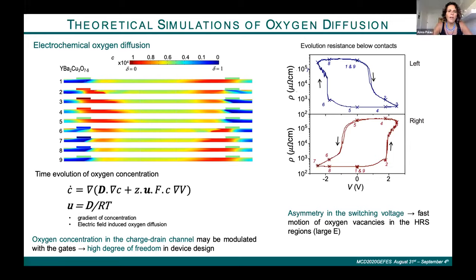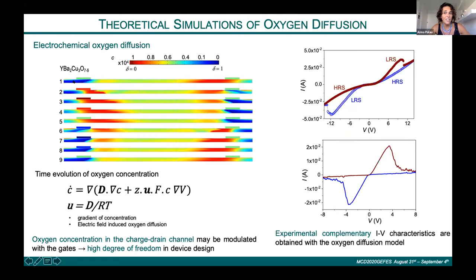Yeah, I think that we have all the effects in the same experiment, and we think it's quite interesting to use different experimental tools to not just evaluate the oxygen content, but also to evaluate the real charge current density and charge ordering, for example in a gradient induced by this kind of experiment, to try to see which kind of transitions are induced. If it's just something that drifts the oxygen, or if it also changes the distribution of the carriers. Yeah. Okay, thanks.